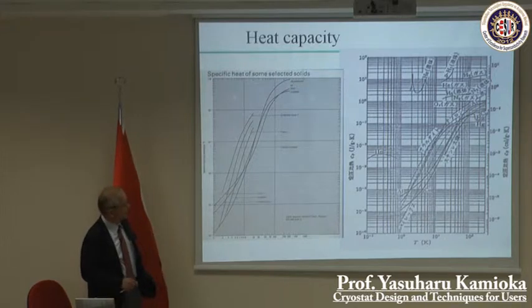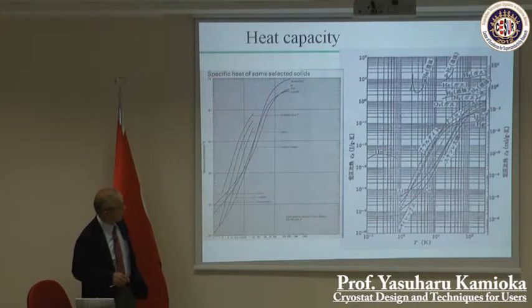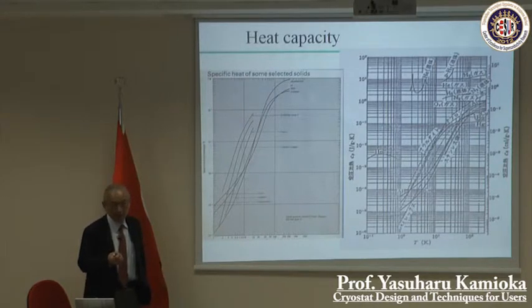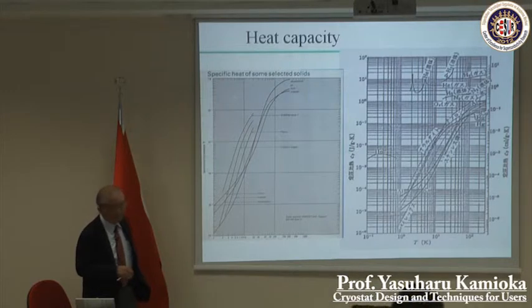This is the heat capacity. It's 100 Kelvin here. Below 100 Kelvin, you have a very low heat capacity in almost all materials. But helium is very high. So when you have something cold inside the vacuum, it is very easy to warm up because of the very low heat capacity.